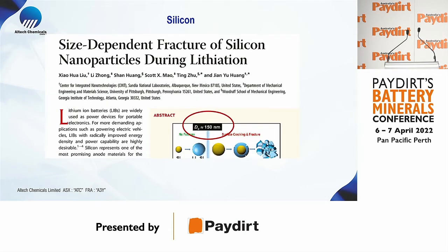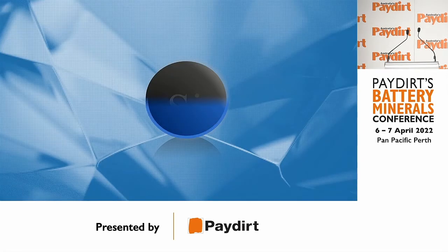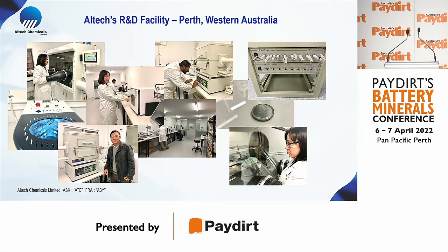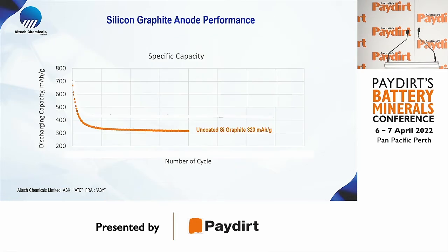Now, the way they've resolved it today with silicon is they've gone to very small particles that don't fracture. So they've gone to 150 nanometers. The problem with that is the cost is exponential. Our technology uses large silicon particles, and what we figured out was, could we use our alumina coating technology to resolve this fracturing problem? So we did all our test work in-house under the leadership of Dr. Jinwan Lui in our labs. And through our testing of 12 months of development, we've come up with a 30% increase in lithium battery.